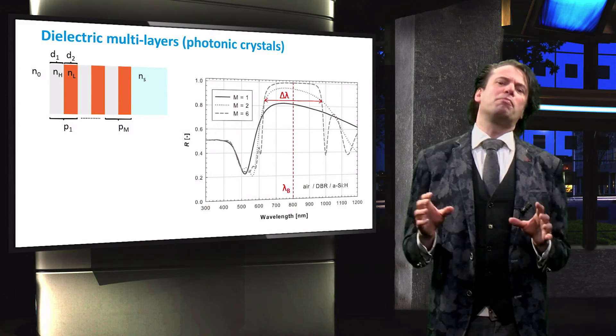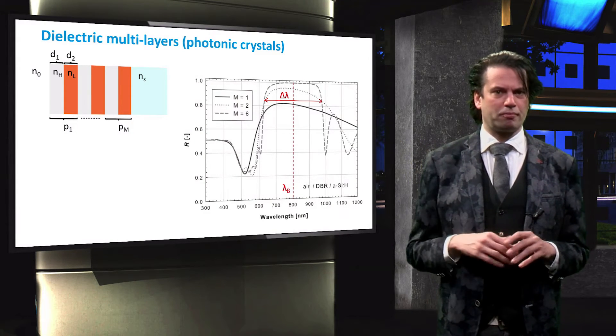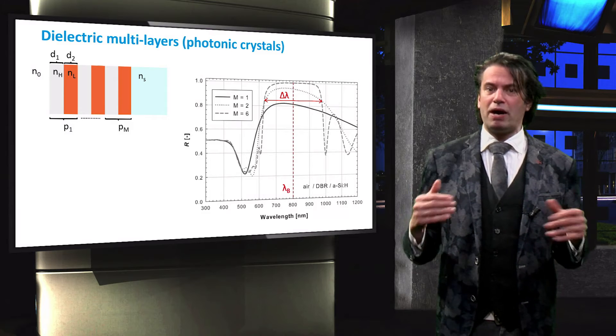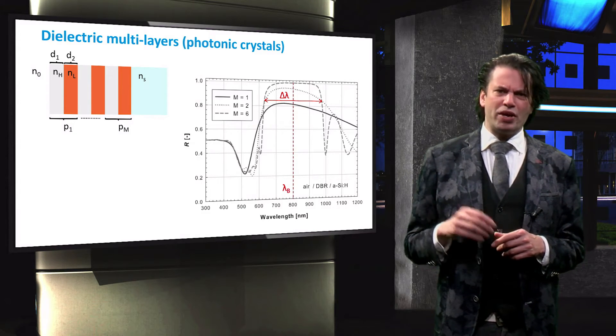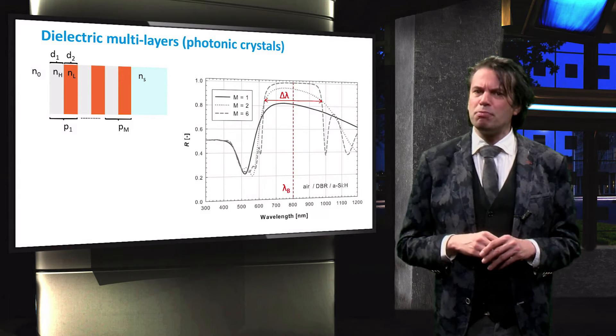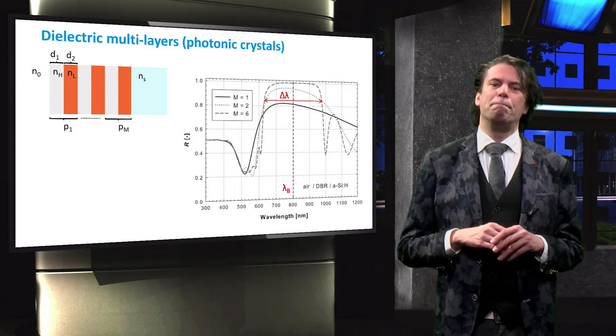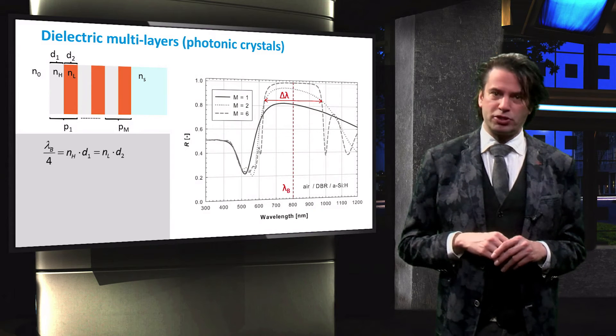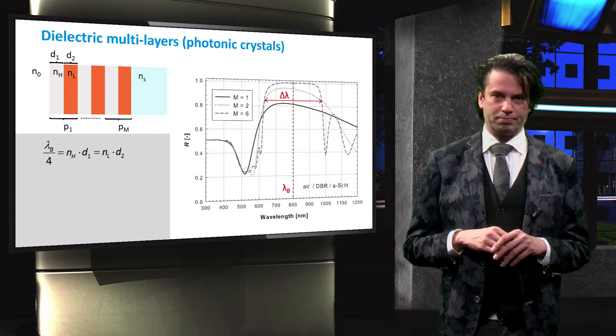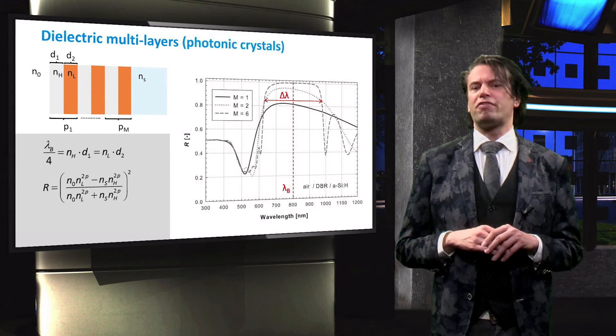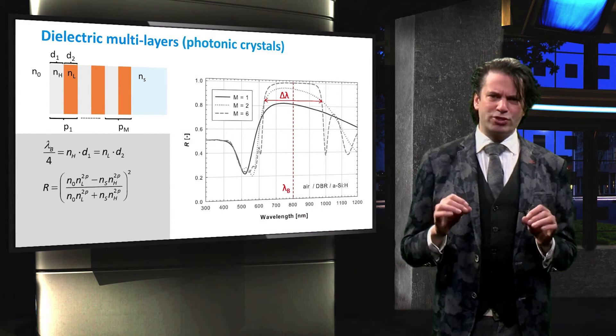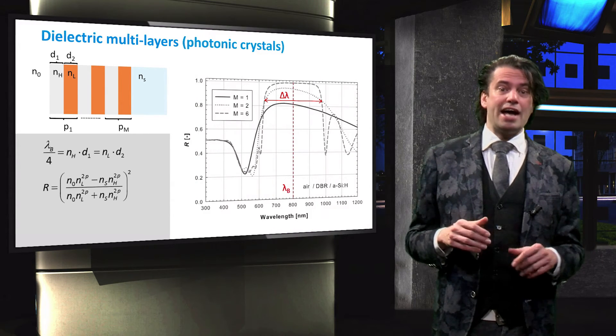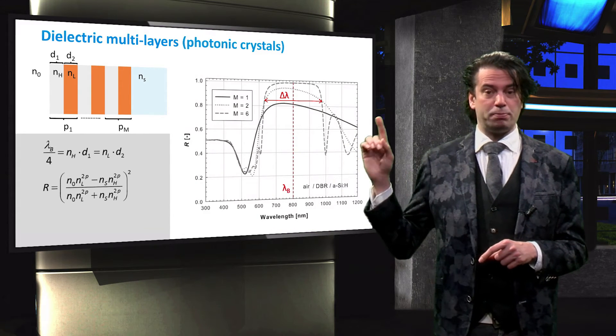So what does the performance of a dielectric backreflector depend on? This graph shows the spectral reflectivity of a dielectric backreflector encompassed by air and amorphous silicon. We can see that the reflectivity is maximal at a certain wavelength λ_b, which is known as the Bragg wavelength. The Bragg wavelength is equal to 4 times the optical thickness of the dielectric layer. The maximal achievable reflectivity at the Bragg wavelength depends on the refractive indices of the dielectric layers and surrounding media.